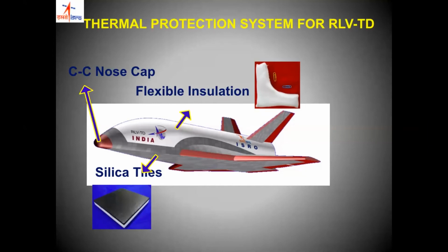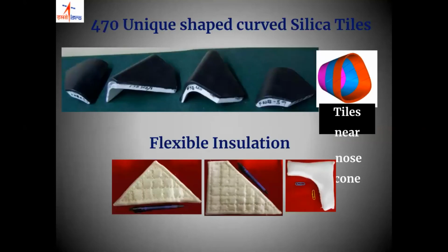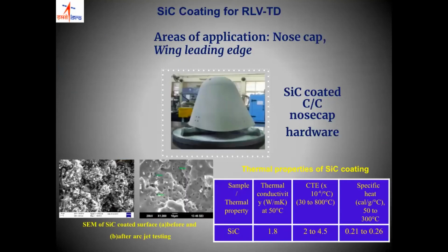So here also tiles were developed. And here the tiles were not only flat types of tiles, or with small curvature. Here different complex shapes of tiles were also realized by machining technique. And wherever there are small to medium temperatures, there are these blankets on the lower side. You can see they were developed for that application. And these are the tiles where we have temperatures around 1400 degrees centigrade. But on the sharp edges, temperatures are much higher, of 2000 to 2500 degrees centigrade.